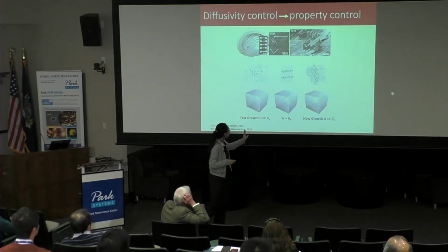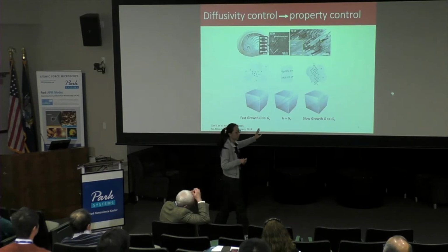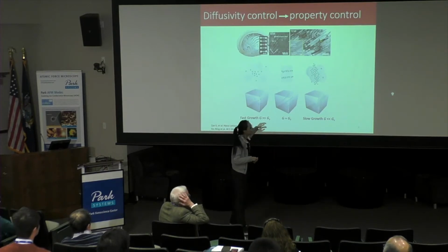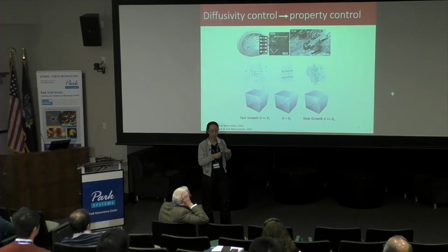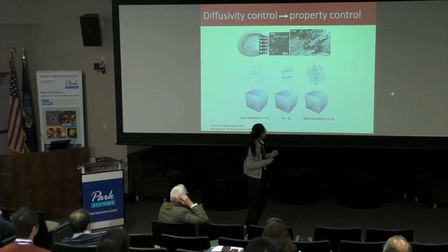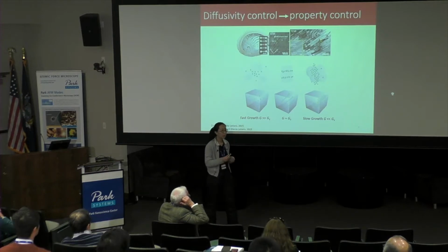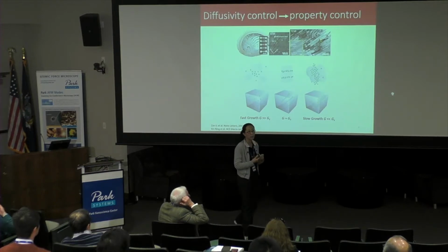If we approach a very slow crystallization rate, the nanoparticles can be aligned between the lamellar interfaces of the crystalline regions. And if we further decrease the crystallization rate, the nanoparticles can be pushed between the spherulite boundaries, like this.